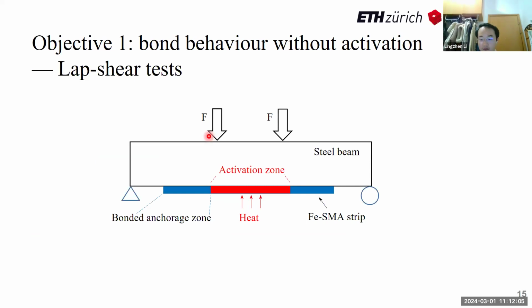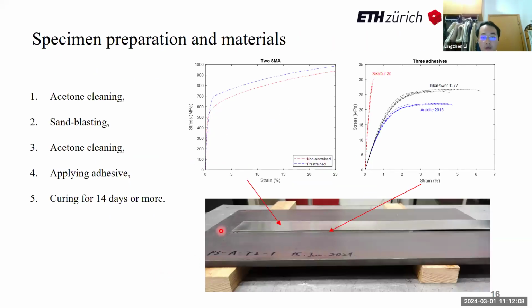Let's start from the first objective. Here is a typical lab shear sample of mine: a shape memory alloy strip bonded by adhesive, this thin layer, to the top of a wide steel plate. The general procedure was that first I used acetone to clean the bonding surface, then used sandblasting to remove the oxidized layer and also to create some roughness for better bonding. Afterwards, acetone cleaning again, then apply adhesive, curing for 2 weeks or more.